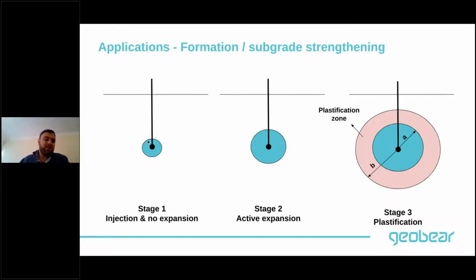These are the stages of this process. You start injecting, and the geopolymer will start filling some void or creating some sort of small bubble with no expansion. As soon as the expansion starts, it will start pushing all the material around it, creating some sort of plastification zone. And that plastification zone will basically increase the relative density and compaction of the soil around the bubble. And you can inject in patterns to ensure that you get the desired strength that you want.